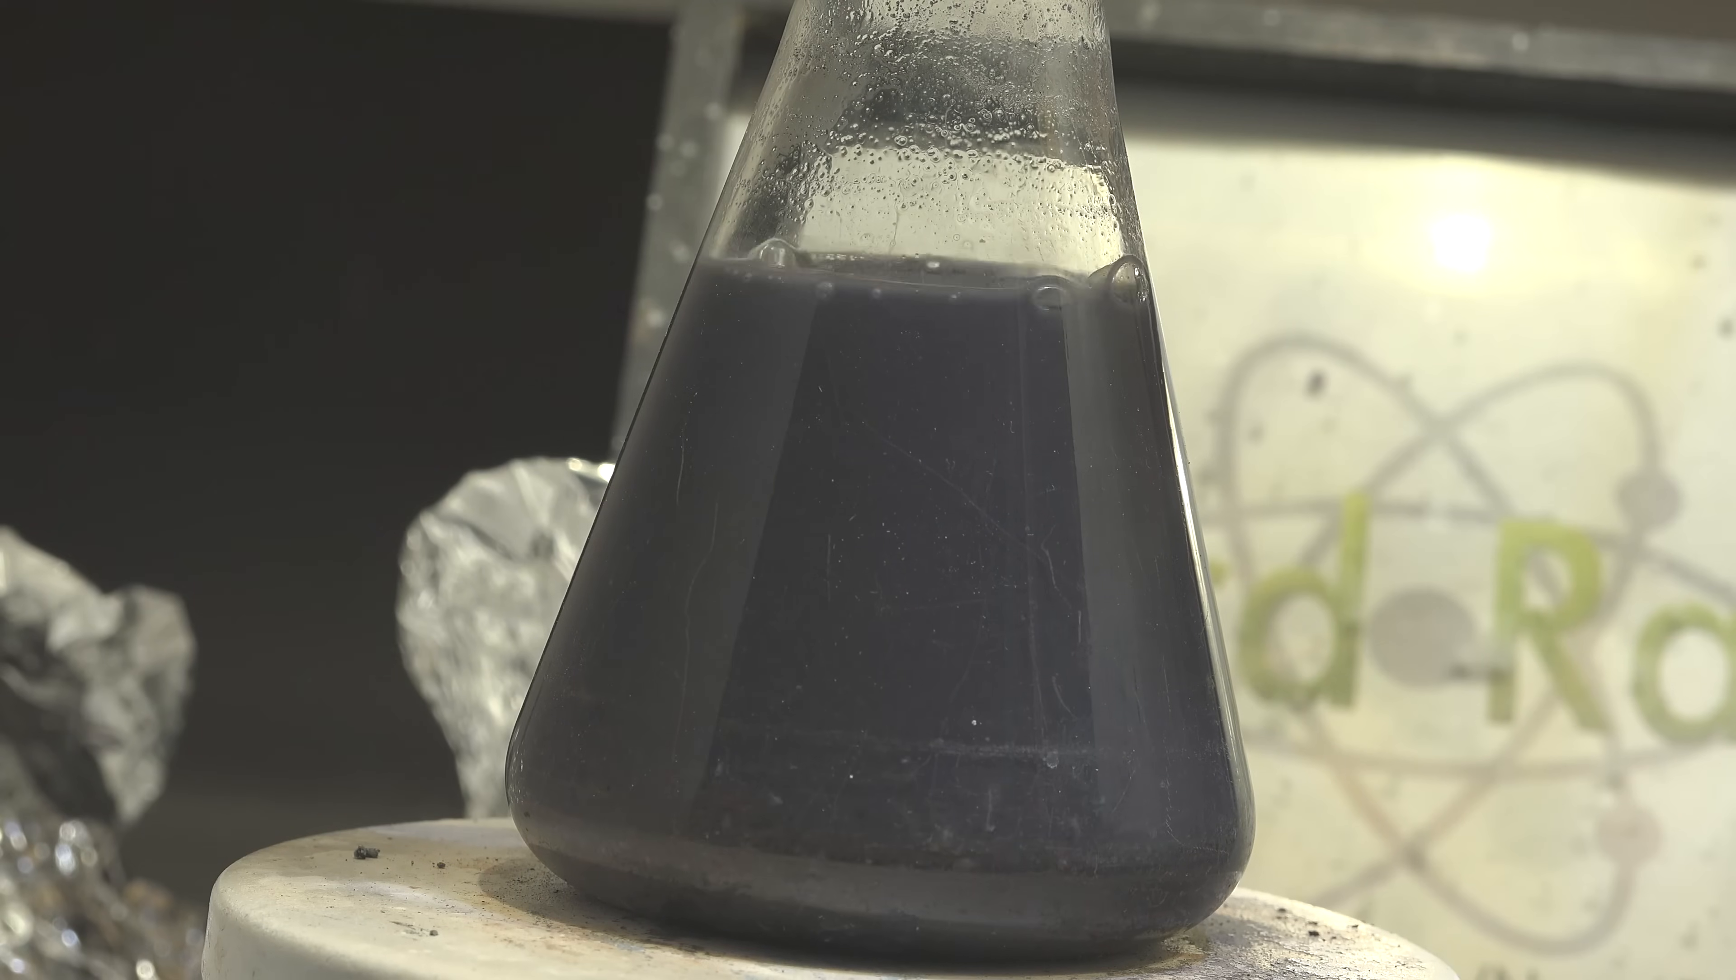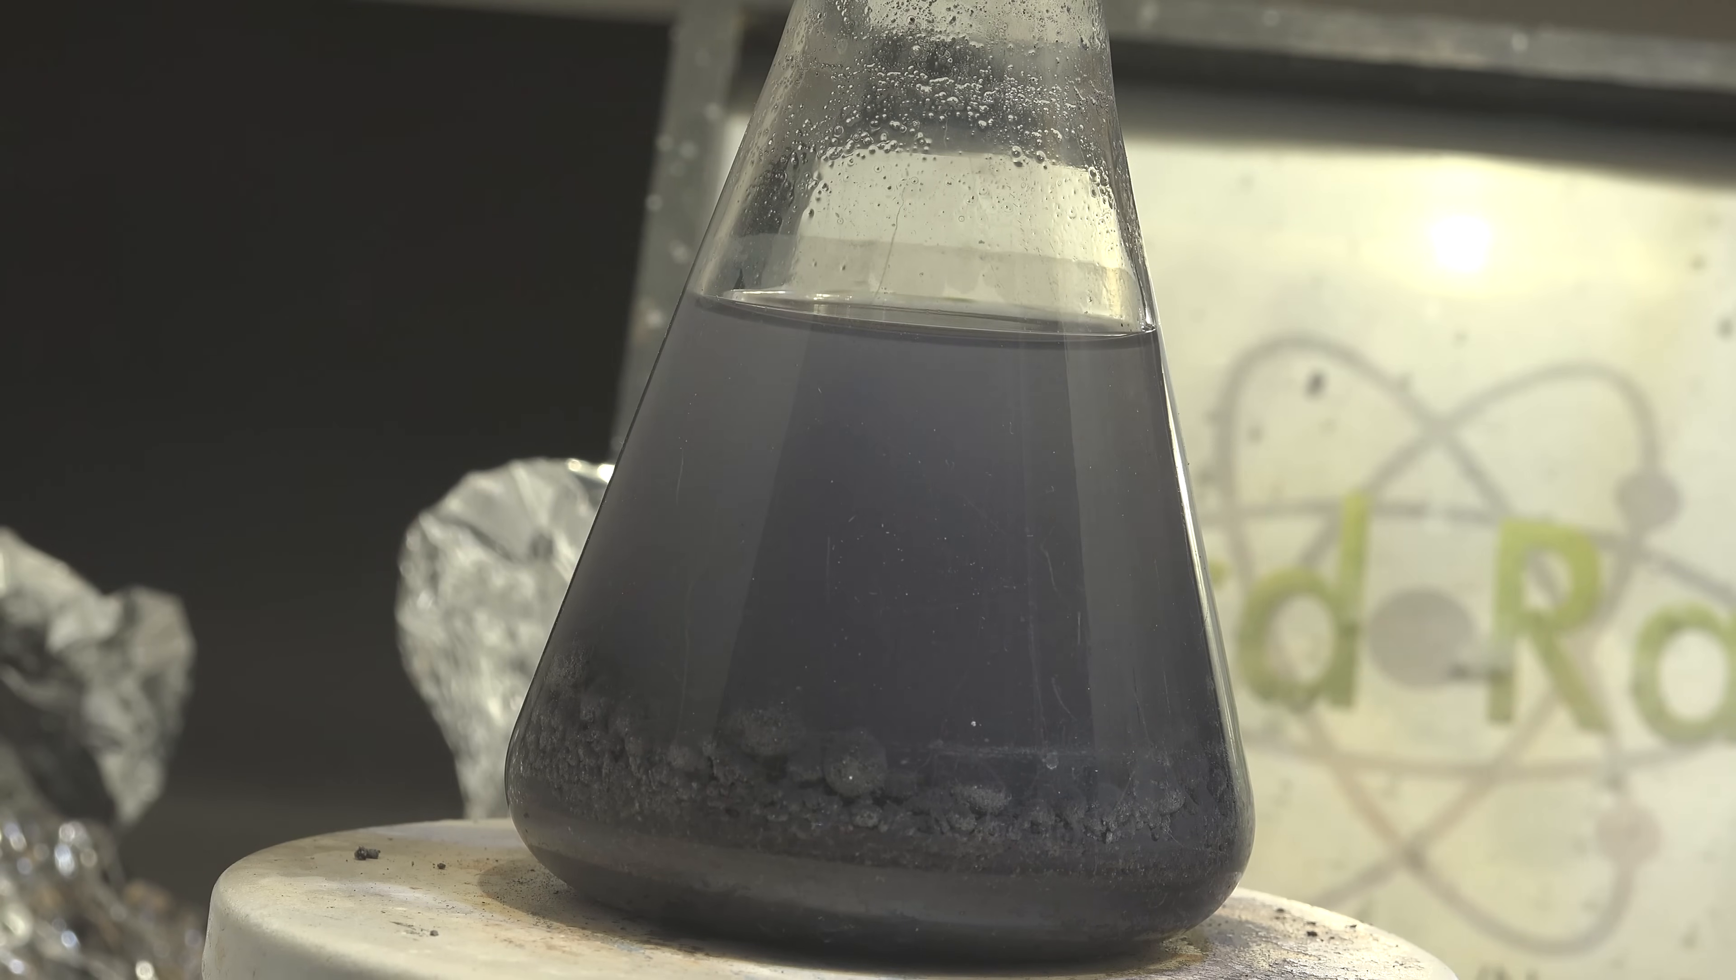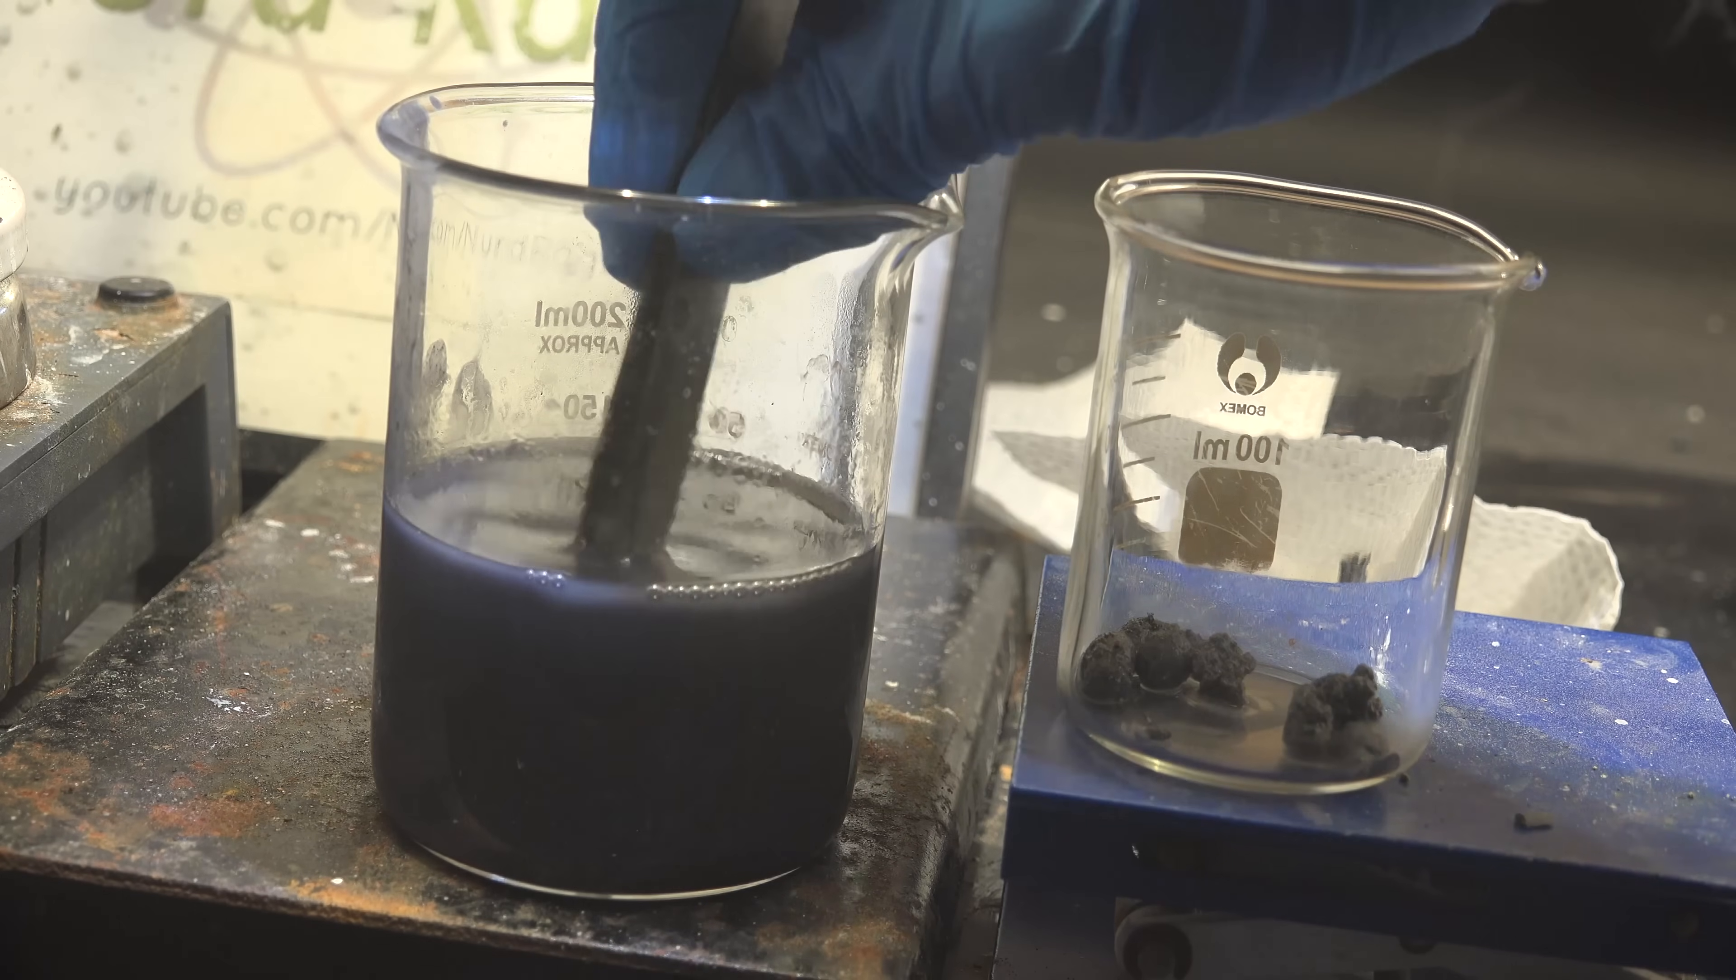Now some of you might be asking instead of distilling would it be preferable to reflux the dioxane and the aggregate and separate the sodium that way. I did try and it does work but I don't like the overall process. The sodium doesn't float in dioxane even though it has lower density because it picks up a lot of the slag as it cools. Additionally when you pour it out you have to deal with the full brunt of the dioxane vapor and you have to manually pick out the sodium.